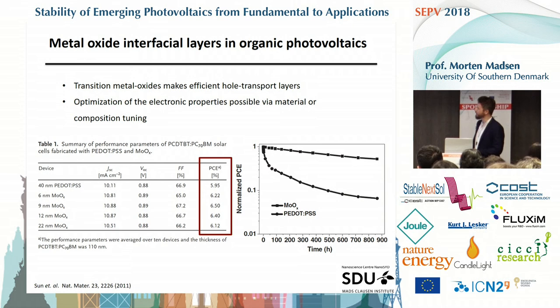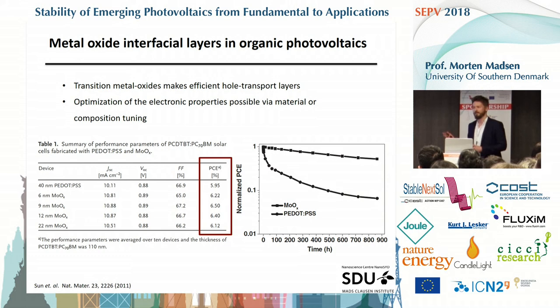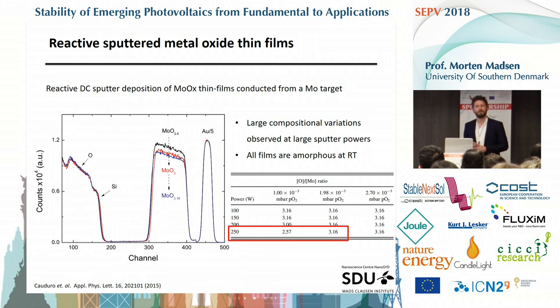Our angle in recent years has been to do some work on reactive sputtering of molybdenum oxide and metal oxides in general. The nice thing with reactive sputtering is that you can tune the composition. What is many times done is that you evaporate the metal oxide—for example, taking MoO3 powder and evaporating it on your active layer or electrode. From reactive sputtering, you put in a molybdenum target and sputter off molybdenum. If you then introduce oxygen into the chamber while you do that, you can tune the composition of your metal oxide.